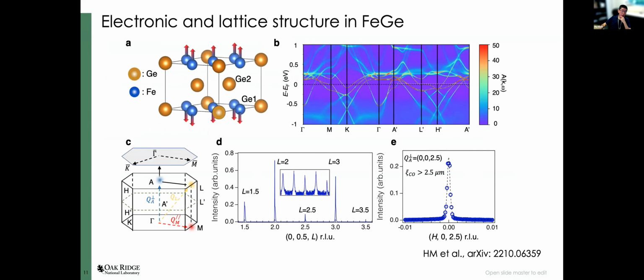To resolve these puzzles, we first carried out a DFT plus DMFT calculation. The first thing we need to understand is the band structure, because at the DFT level, from previous studies, it seems hard to understand. After you put in the DFT plus DMFT calculation, everything can be reasonably described within this framework, and you do see the saddle point pushed to the Fermi level. This effect is partially related to the correlation, and also partially related to the AFM ordering. Meaning, if you don't have AFM long-range order, the saddle point will not be close to the Fermi level. So that's an indication that AFM, in the bottom line, is going to push your saddle point to the Fermi level, which may contribute to the CDW.